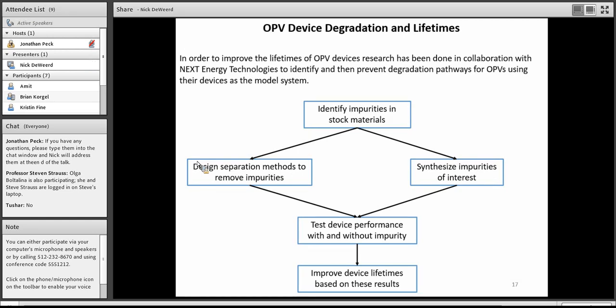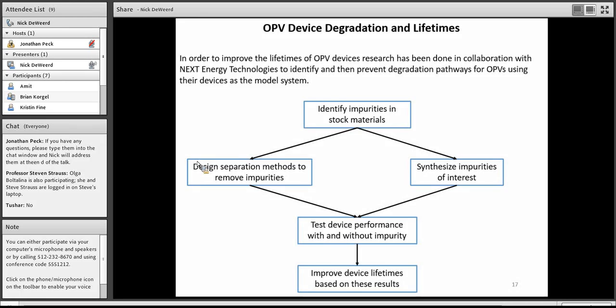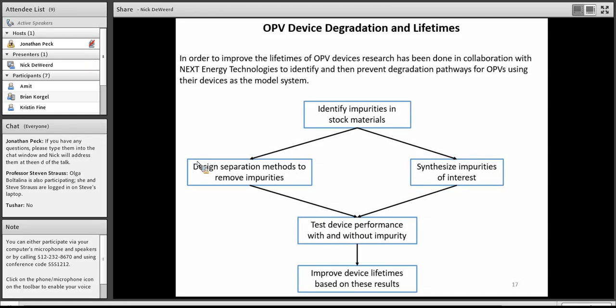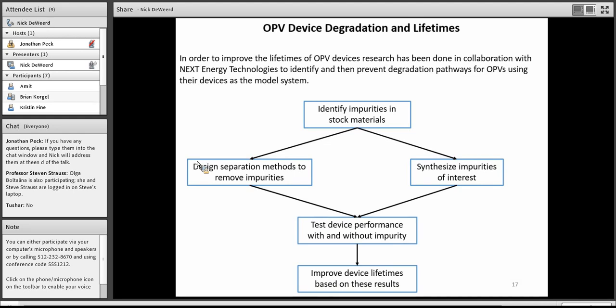One of those aspects of this work is to focus on the inherent impurities in the stock materials. Any commercial chemical is going to have some impurity present. Nothing is ever 100%. So what we've been doing is trying to characterize and identify what these impurities in these stock materials are. Once we've identified that they're present or identified what impurities they are, we can either then synthesize those impurities or we can design separation methods to remove the impurities from those stock materials. Then we can make devices and compare performance with and without that impurity so that we can decide whether or not these impurities are actually detrimental to device performance. Because obviously if an impurity does not negatively impact device performance, then there's no need to make an effort to remove it or design ways to minimize its effect on the device. That would of course have a net end result for improving device lifetimes based on the work that we're trying to do.